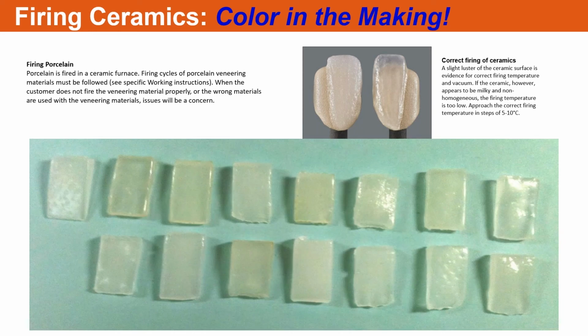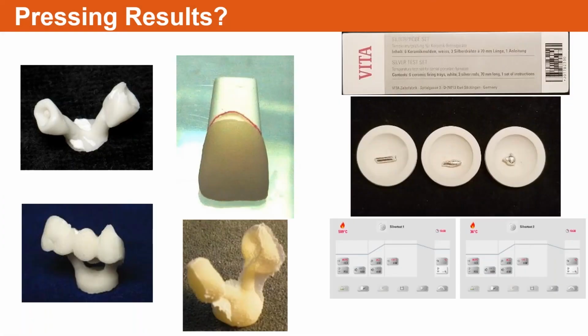If you don't, no matter what we do when it comes to ceramics, anything pressed material, glass material, it will be discolored when it comes out. These are all supposed to be clear, but only one or two actually look like they're clear. The rest all have contaminants within that muffle, and it changes to more of a yellowish tone, that clear window. And so when you're looking at shade, it could be just contamination of your furnace that you need to watch out for. You can also do a silver test.